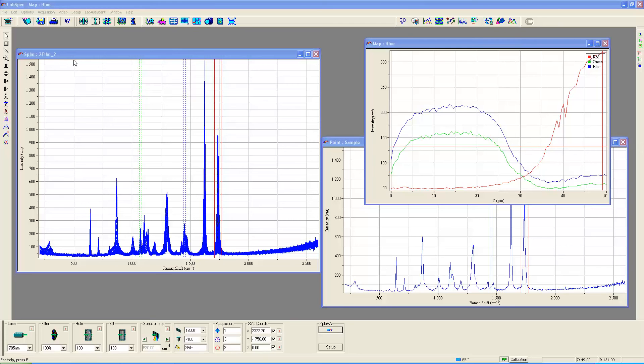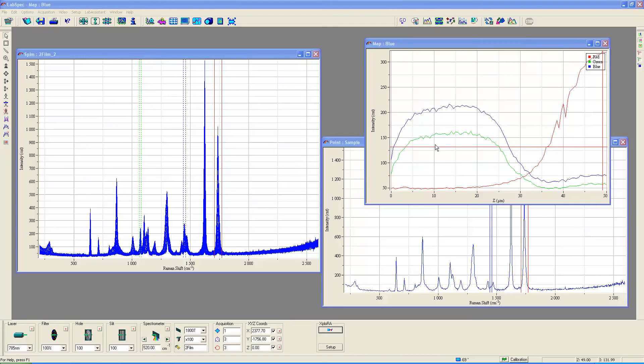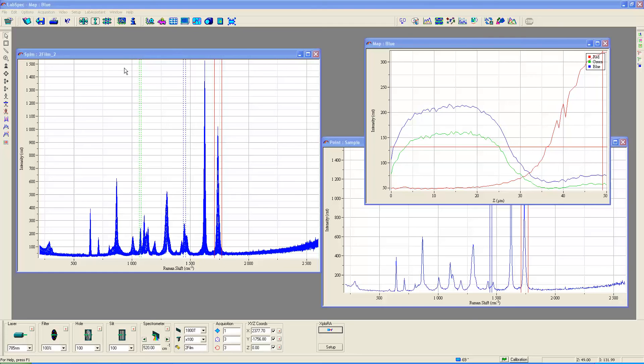What you're looking at now are data in a data set called two film underscore two which was obtained with the laser beam incident upon this two-layer film and parallel to the normal of this two-layer film. I began with the beam focused approximately at the surface which would be at the polyethylene, at approximately the zero position, and then moved the stage up which is to say moved the focal plane of the microscope objective and the laser beam down through the two-layer sample.